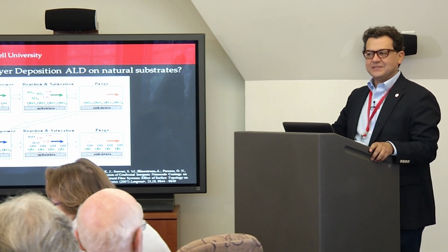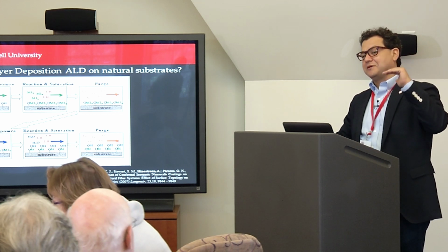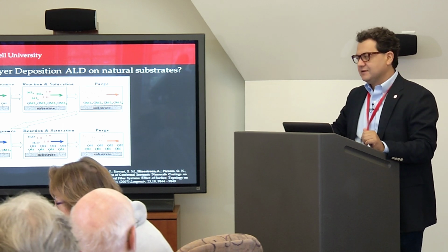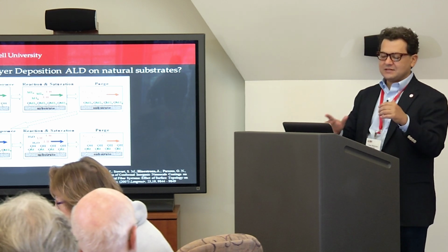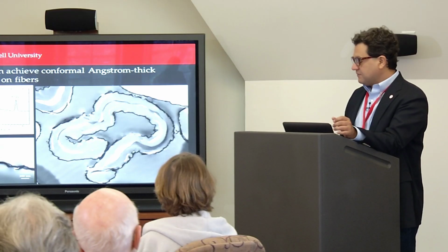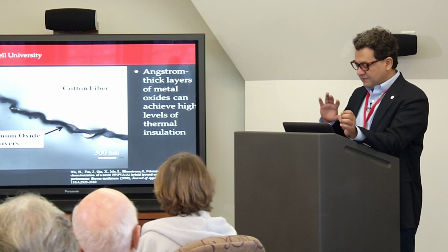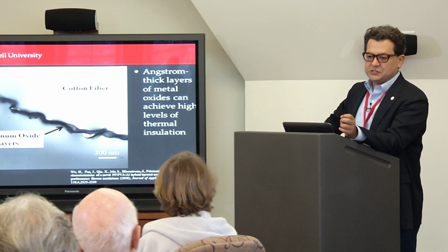Correct. So we are about 10 times smaller than those interactions. So we are using the molecular control we have, but on large surfaces. And that's the beauty of cotton. So we made these layers, and these layers are only 50 angstroms. These are very, very small. And now we can have these layers, and they have a very large amount of thermal insulation.